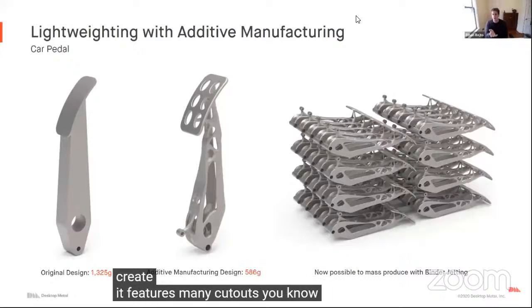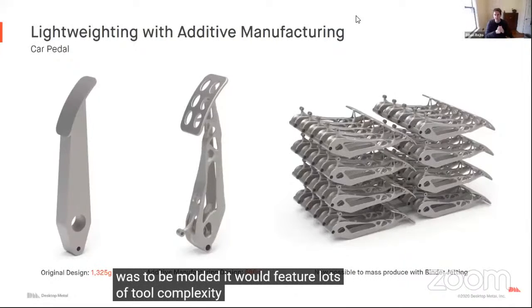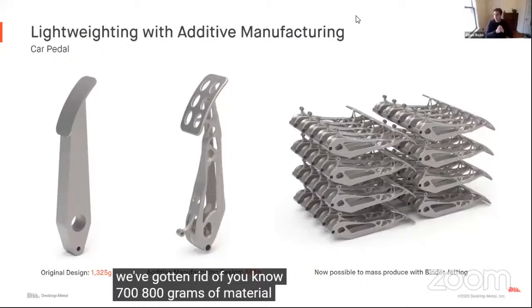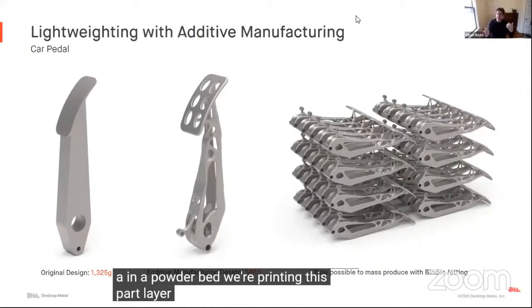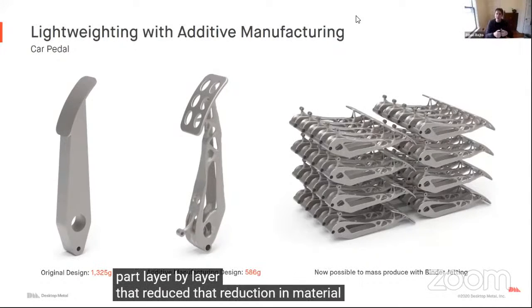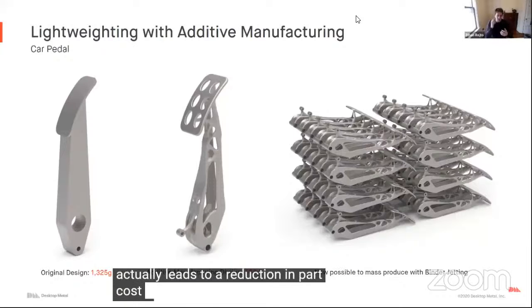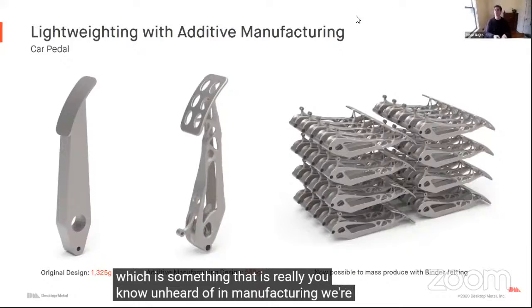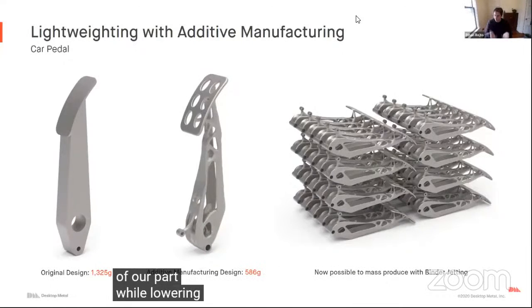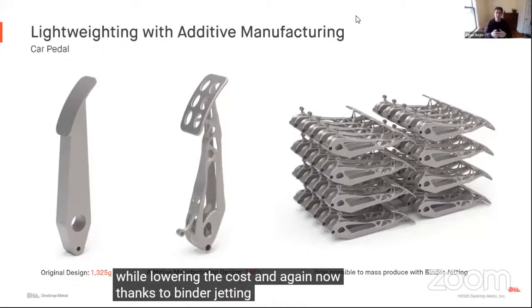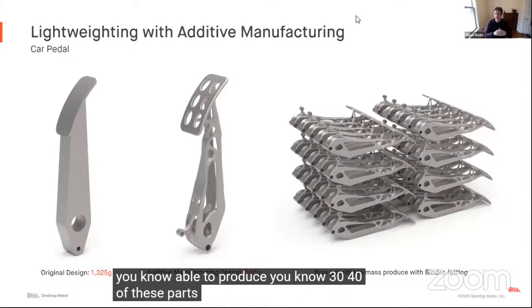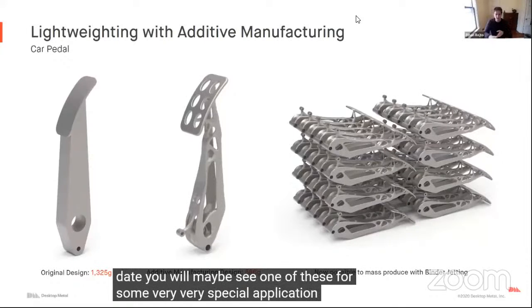It features many cutouts. If it was to be molded, it would feature lots of tool complexity. But with additive manufacturing, now we've gotten rid of 700, 800 grams of material. That's going to result in savings on the part, because since we're printing in a powder bed, we're printing this part layer by layer. That reduction in material actually leads to a reduction in part cost, which is something that is really unheard of in manufacturing, where we're actually able to increase the complexity of our part while lowering the cost. And again, now thanks to binder jetting, we can actually mass produce parts that look like this. Able to produce 30, 40 of these parts in just a few hours, where to date you will maybe see one of these for some very, very special application.